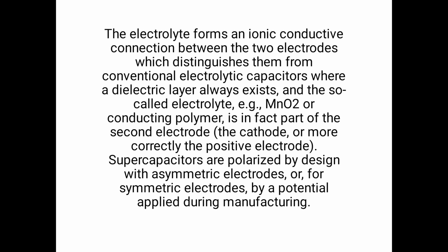The electrolyte forms an ionic conductive connection between the two electrodes, which distinguishes them from conventional electrolytic capacitors where a dielectric layer always exists, and the so-called electrolyte, MnO2 or conducting polymer, is in fact part of the second electrode, the cathode, or correctly the positive electrode. Supercapacitors are polarized by design with asymmetric electrodes, or for symmetric electrodes by a potential applied during manufacturing.